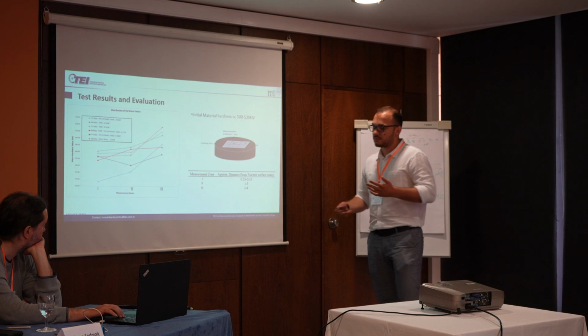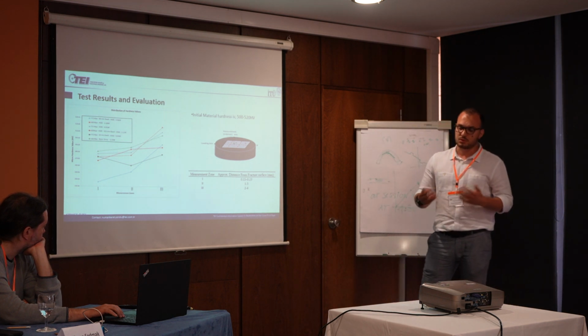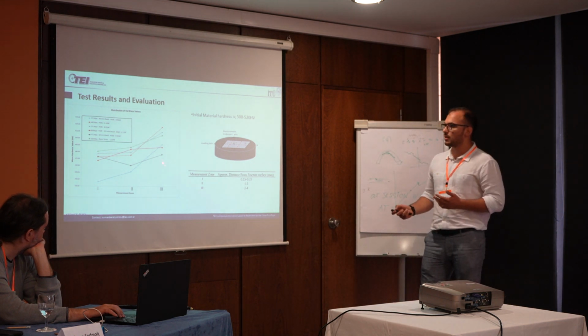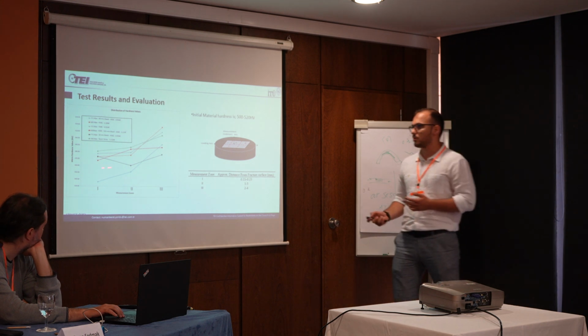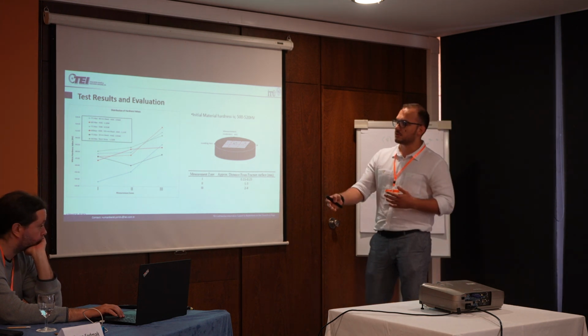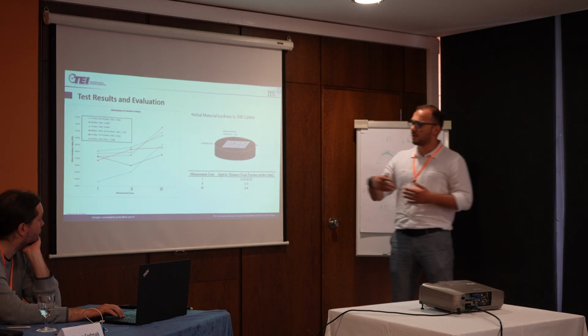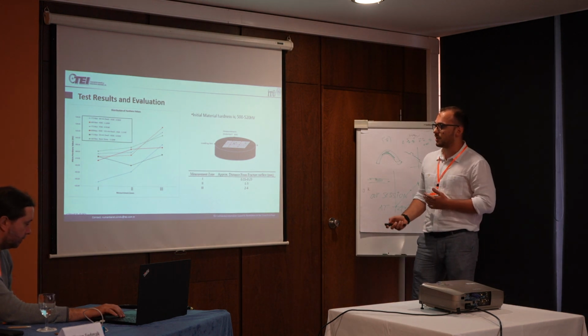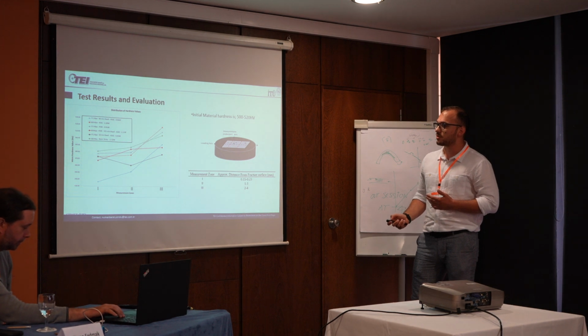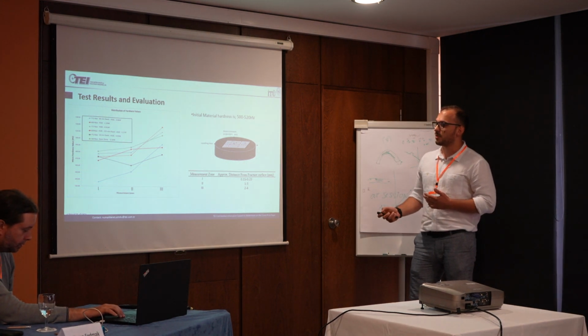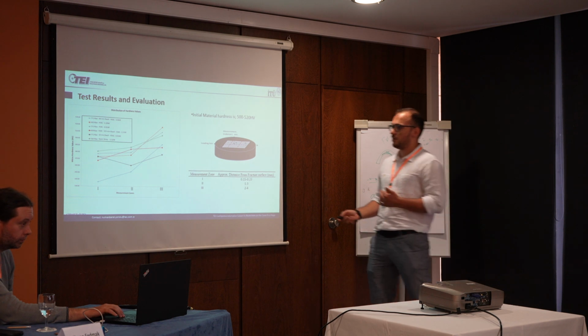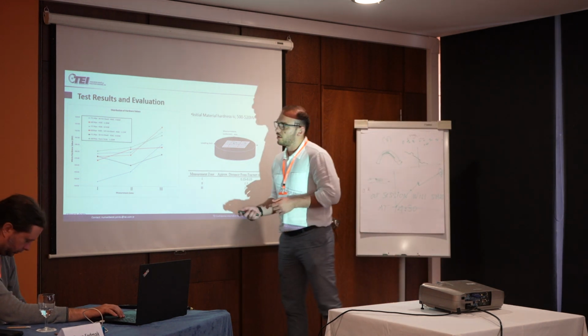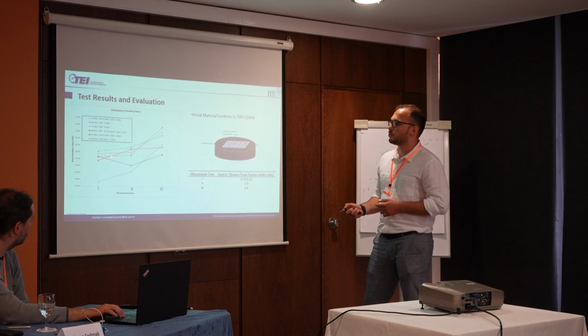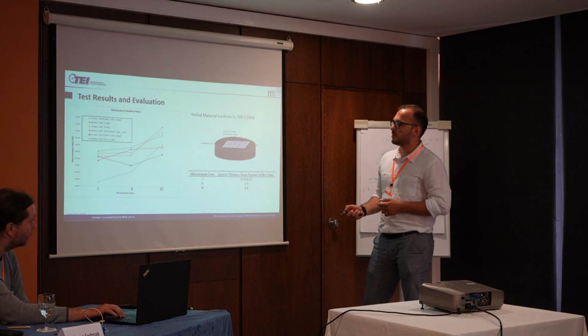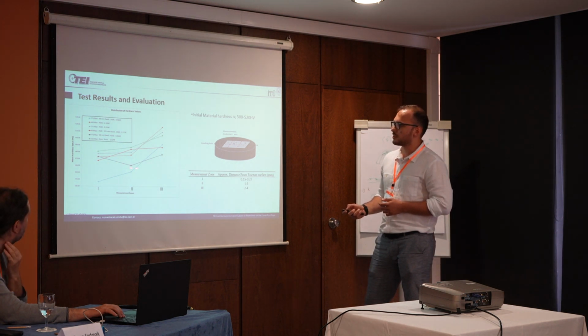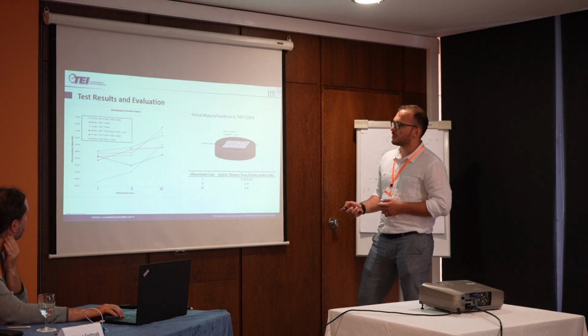Maybe we can't conclude it as softening, but there is a decrease in the hardness values once we reach the fracture surfaces, and this decrease in the hardness is also affected by the applied stress and applied dwell. Here, I can show you that, for example, this black line has a little scatter, but this black line is lower than the